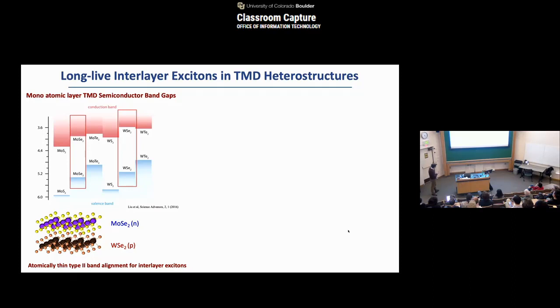When we put them together, molybdenum diselenide is N-type, tungsten diselenide is P-type. So immediately when we create this exciton and bias it, like the semiconductor heterostructure case, we expect to see that an interlayer exciton can form across this type of layer, right?